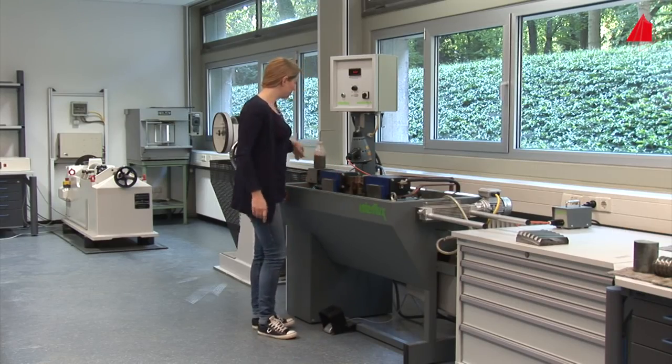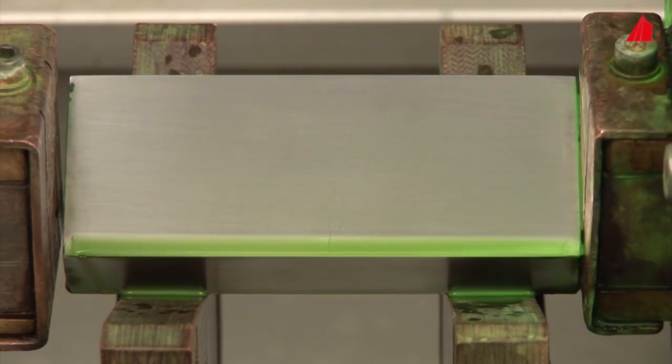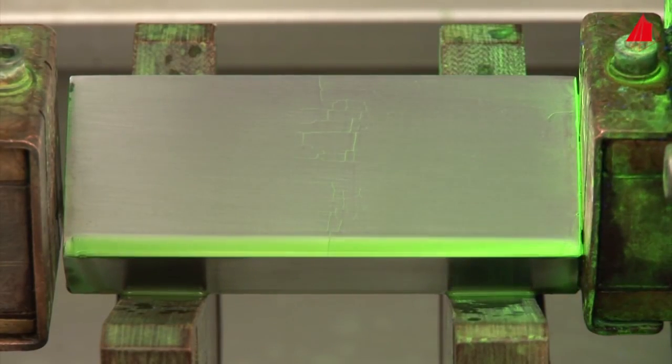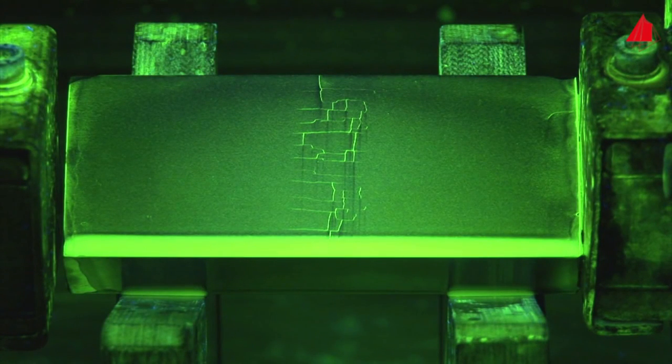Already in daylight, dark lines are visible on the surface. The lines can be seen much better under ultraviolet light, and particularly well when darkening the daylight. The suspension contains pigments that cover the magnetic particles and fluoresce under ultraviolet light.